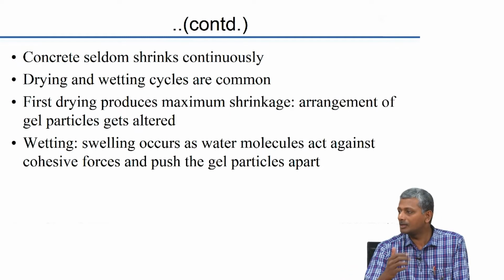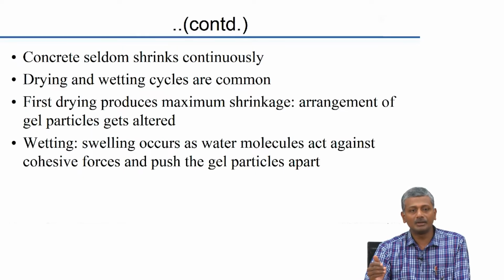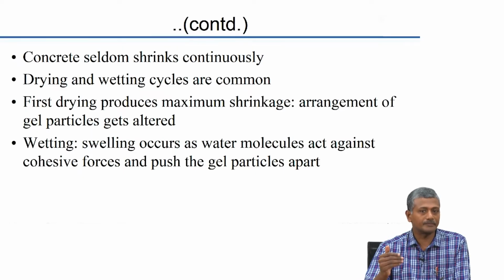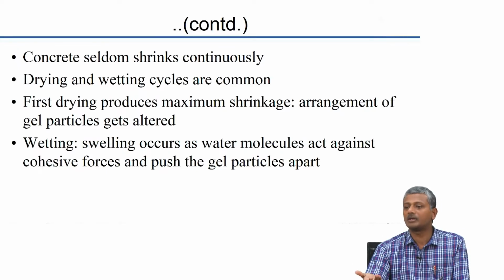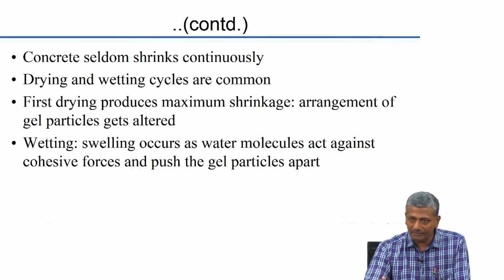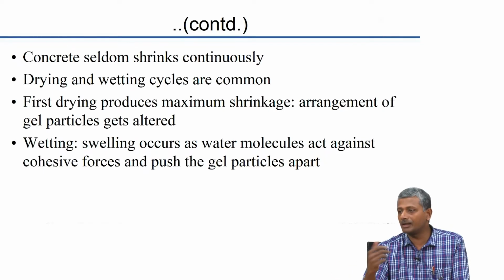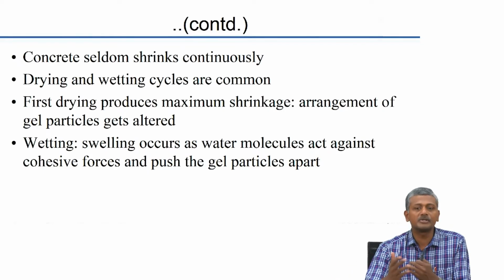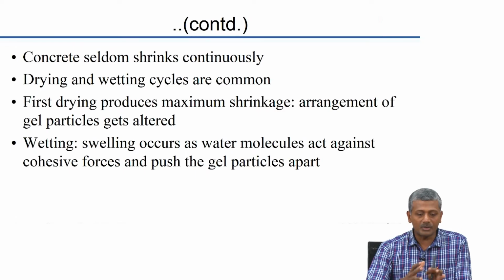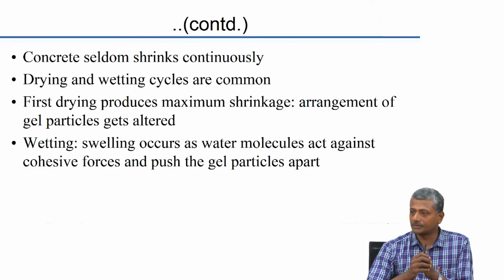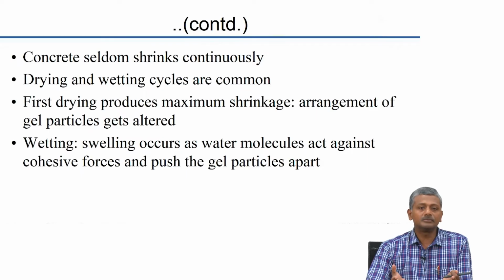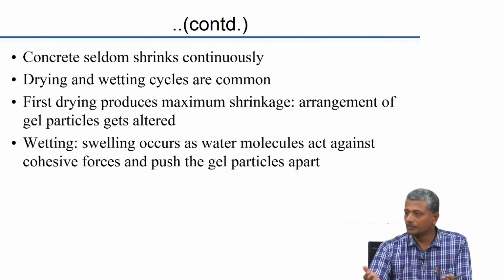But there we do a continuous drying at low relative humidity to make the concrete shrink continuously. But then in reality this concrete shrinks for some time and then there may be a rain after that because of that there is re-wetting, and then there is going to be drying again and re-wetting again and so on. There will be multiple cycles of drying and re-wetting. So, how does this affect the concrete structure? As you can readily imagine, when the concrete is just removed from your moist curing environment and subjected to the first drying, you can expect the maximum amount of water to leave the system.